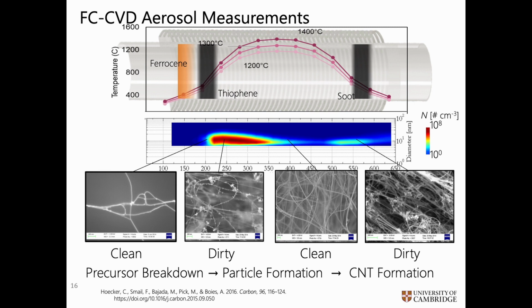But one of the interesting things, in our first big finding in this field, was that actually our catalysts go away. And that maybe is not so much of a surprise if you think about it, in that as a reactor gets hot, it can evaporate more material. So you can think of the gas as having a greater capacity to store more gas phase iron particles or iron molecules, just like when you put sugar into your tea. If your tea is cold, you can't absorb much of the sugar, but if you heat it up, you can absorb all of your sugar. The same happens in a gas. And so we can absorb all of the molecules eventually, depending on the recipe, into the gas phase.